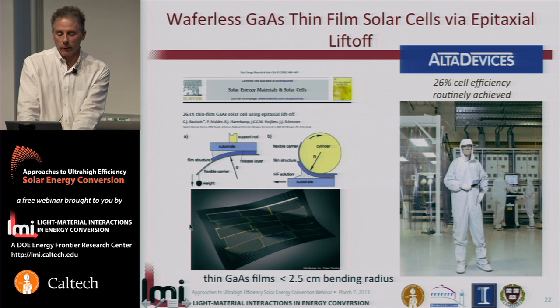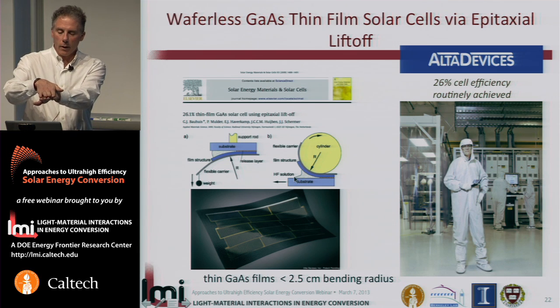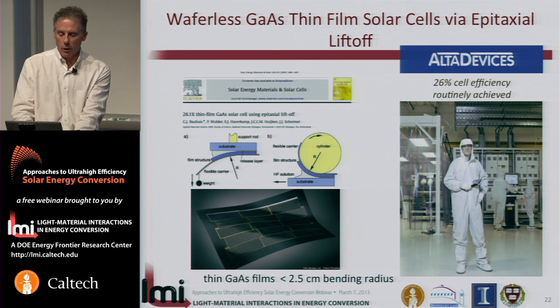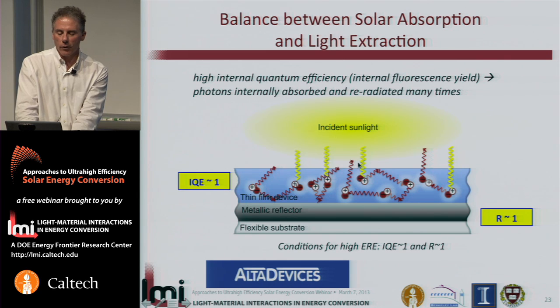And in order to efficiently leverage the ability to make single crystal cells and do that in a cost-efficient manner, we utilize a process in which cells are peeled off their growth substrates by an epitaxial lift-off process, very similar to the way a sticky note would be peeled off a pad of sticky notes. But in this case, the thin note here is a single crystal film of gallium arsenide that can be fashioned and processed into a solar cell. And that solar cell is made of a material that has very high radiative efficiency, and by virtue of the lifted off cell design, has a highly reflecting back reflector.